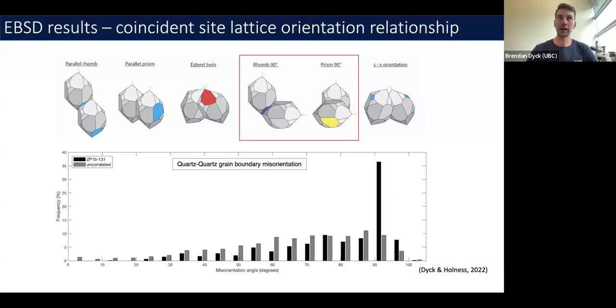We can look at it from a more statistical perspective here, focusing just on the Rhomb 90 and the PRISM 90. The EBSD data will not tell us whether we're meeting on the Rhomb plane or the PRISM plane, but it will tell us the orientation relationship between the two crystals. So if both of these are at 90 degrees to each other,